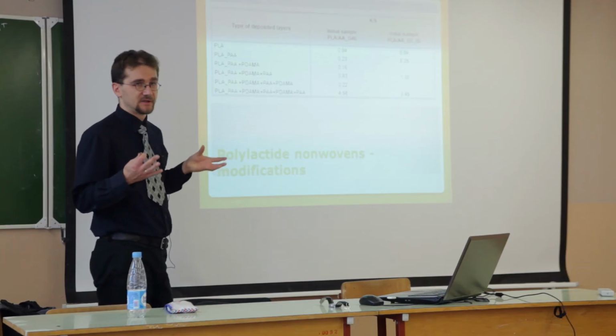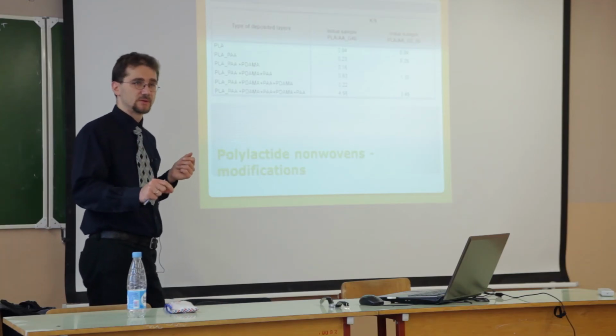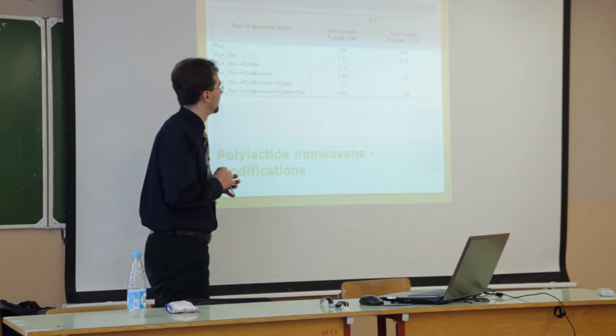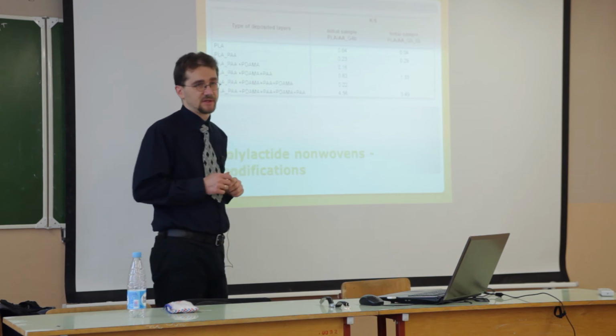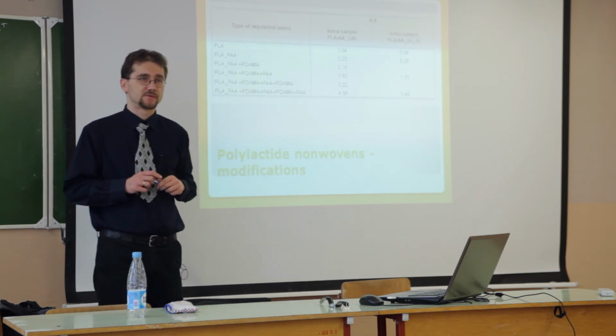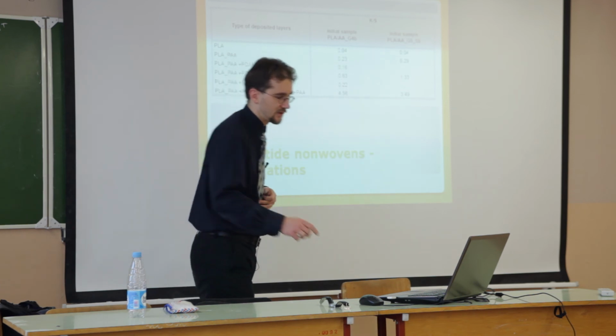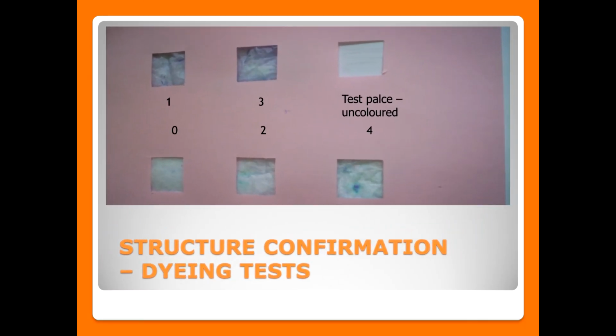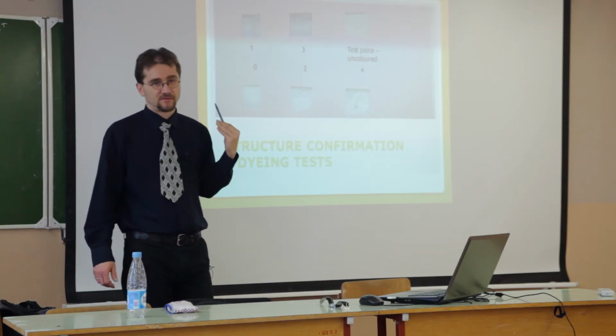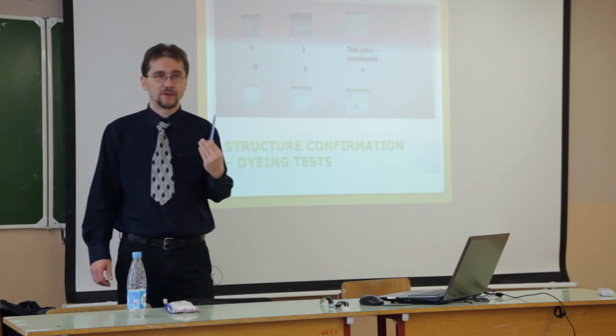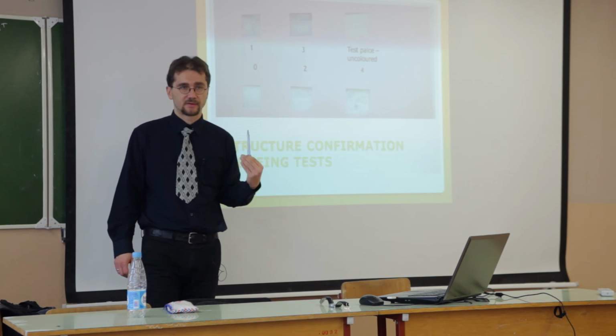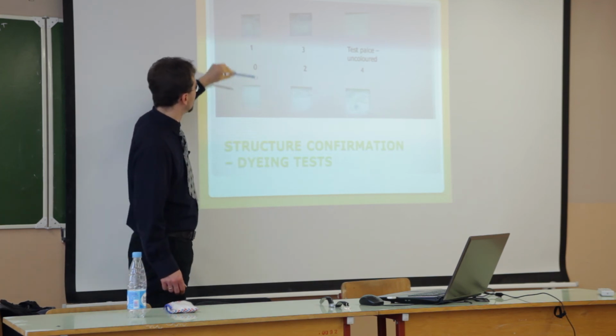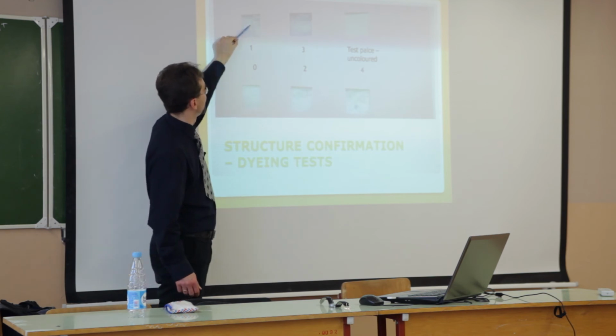The color is visibly different when we dye this material with methylene blue dye, and the changes in color we can measure. We have a special apparatus for that, and we can calculate the Kubelka-Munk relationship, as you can see here. The unmodified material is probably too bright to see the differences. Methylene blue is used for dyeing surfaces which can have an acidic character, so this one should be blue. This is unmodified, white. After grafting, more blue.